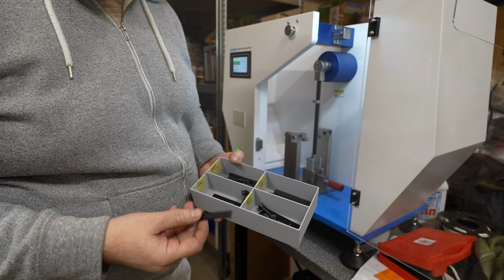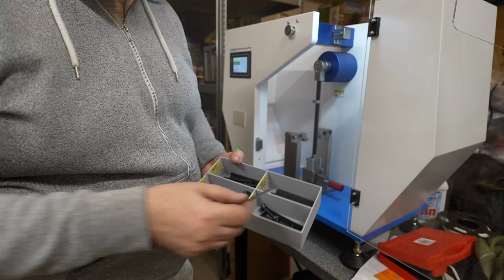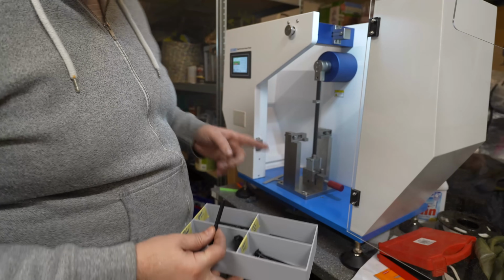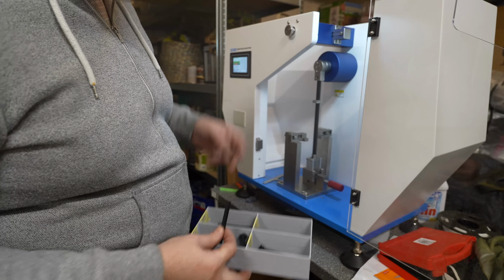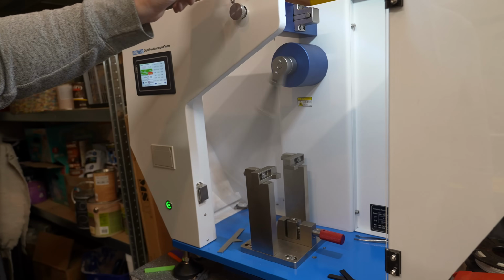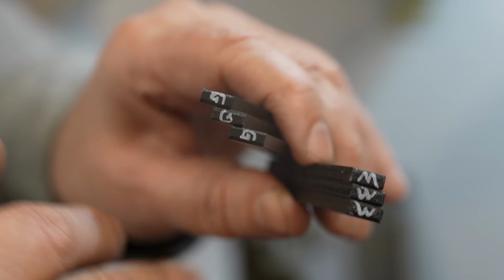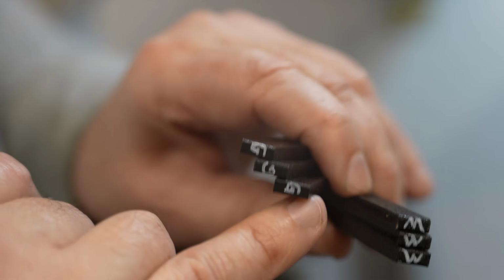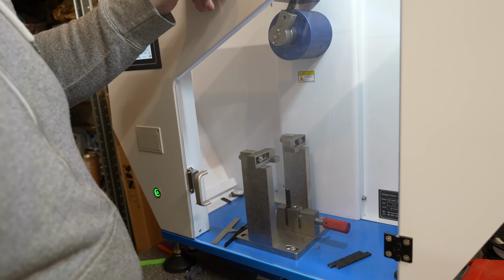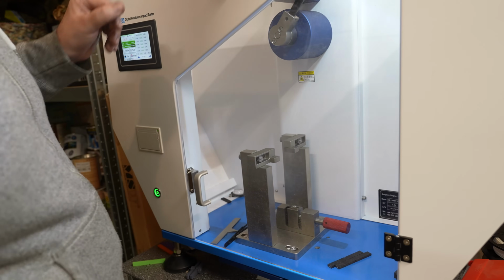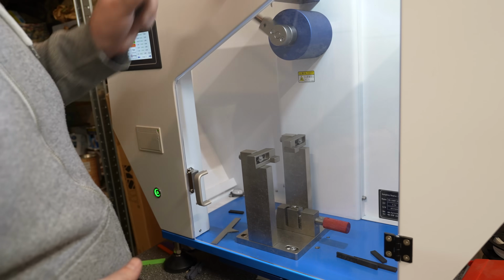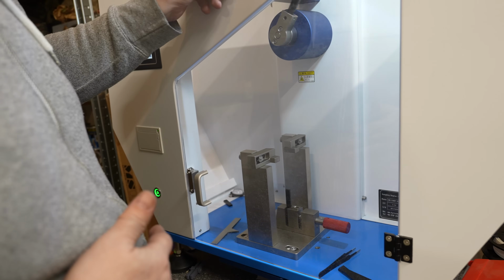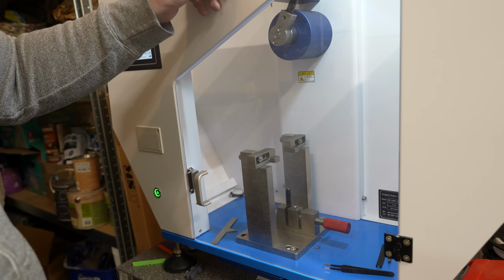Now the IZOD impact test, and I will show you just one break from each material, and then I will show you 4 pictures from the screen with 3 results. PLA, PETG, but for this test I have before and after drying. PETG wet, PETG dry, ABS, nylon.